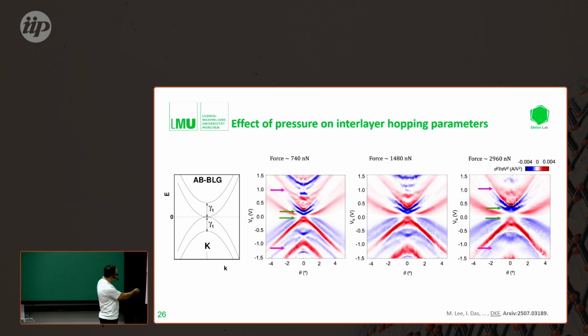These lines here correspond to the nesting conditions of these higher energy bands, and you can see that if we press, these bands are pushed out in energy. So really, with just this technique, we can control the band structure of the material with pressure. And I think this will be particularly interesting later on if we can do tunneling into the superconducting phase. It would be very interesting to see how the superconducting phase changes under pressure.